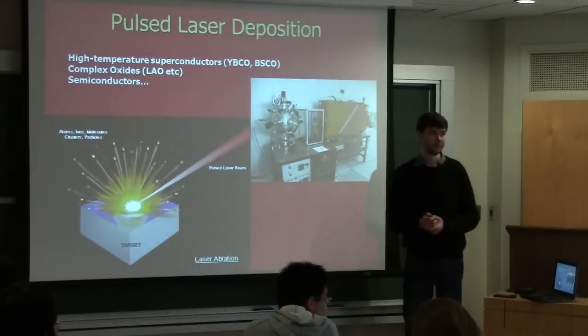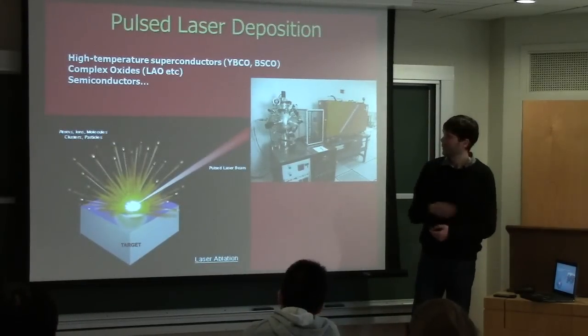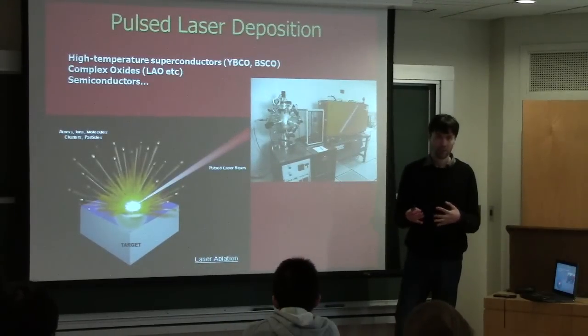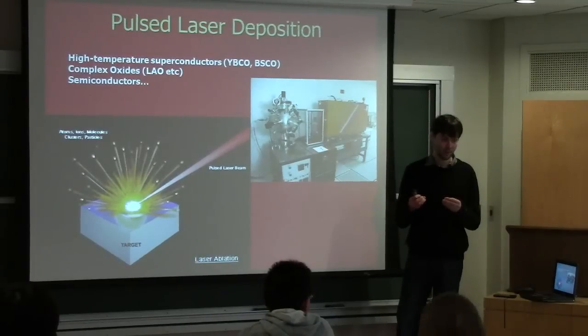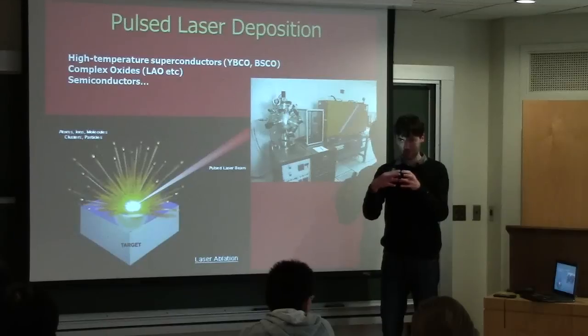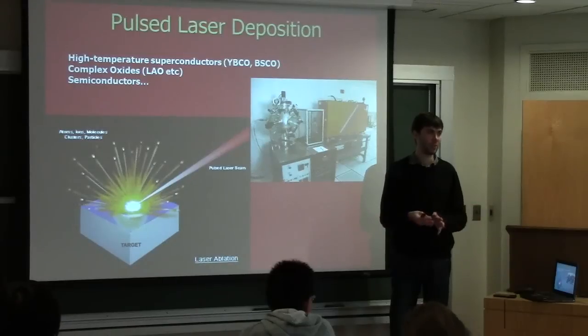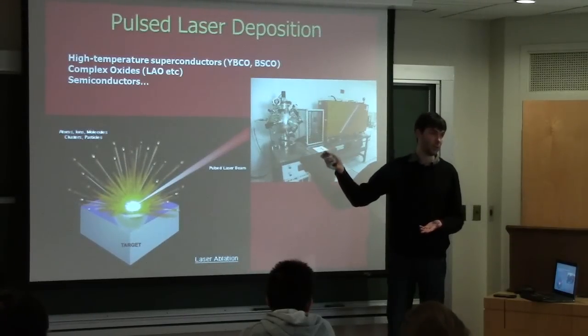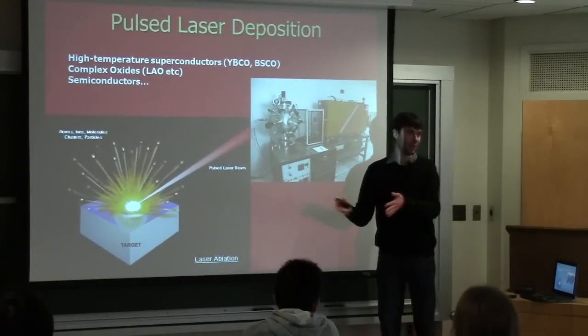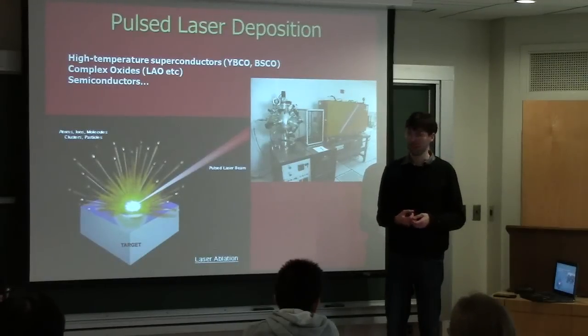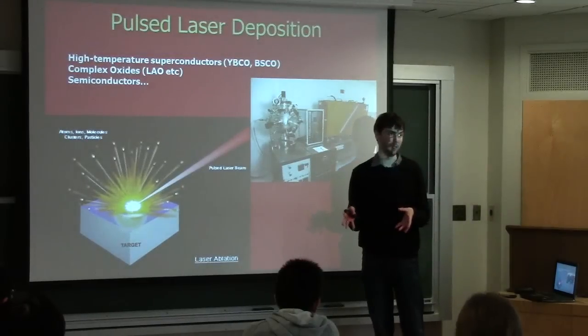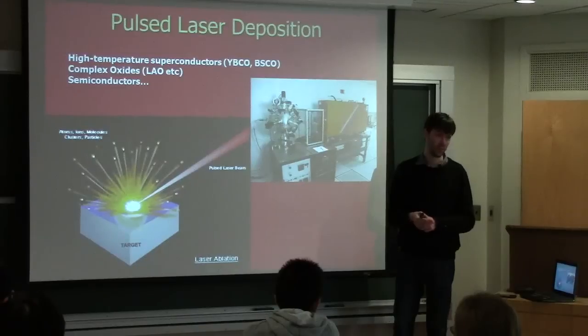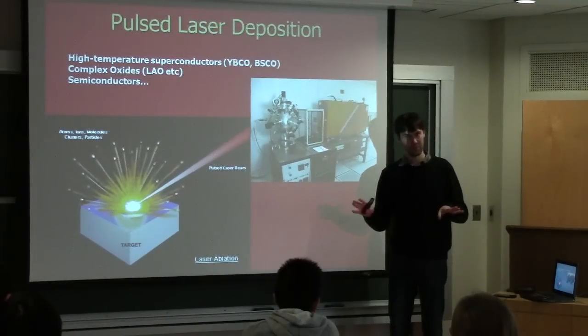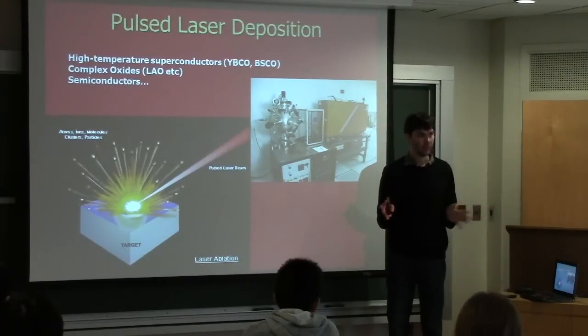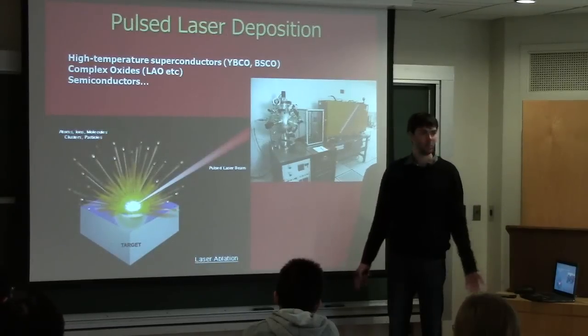How does it compare to MBE? Well, I think in these complicated crystals, there are many internal degrees of freedom where atoms can move slightly, or the crystal cells can even turn positions a bit, and there's not much you can do about it. They are also not stoichiometric. Often you want to dope them with oxygen, and so the amount of oxygen varies per cell. And so I think even if you were able to tune up epitaxy for these films, and some people do, there are groups that I think also do epitaxy. Still, the film quality is not exceptionally better. Better with epitaxy, but not orders of magnitude better. So I think there is a certain advantage to just having a target and blasting it.